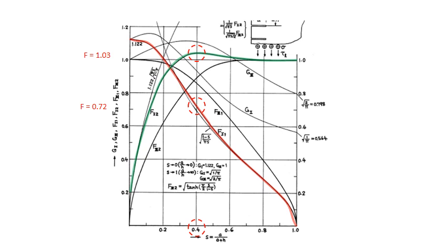Now I highlight these areas a little bit that are really key sections. When your green curve peaks at S equals 0.4, our red curve, if you drop down, is lower down. We have a different compliance factor to use for our classic solution. So if we were working with the green curve, we would be looking at a compliance factor of 1.03. But if we want to translate everything into our standard red curve, then we've got a compliance factor of 0.72. A little bit tricky to wrap your head around, but we'll just have to sort of plow on.